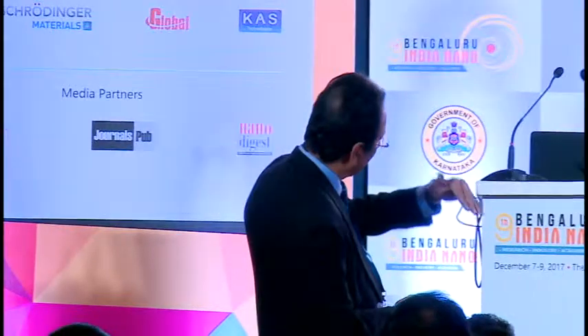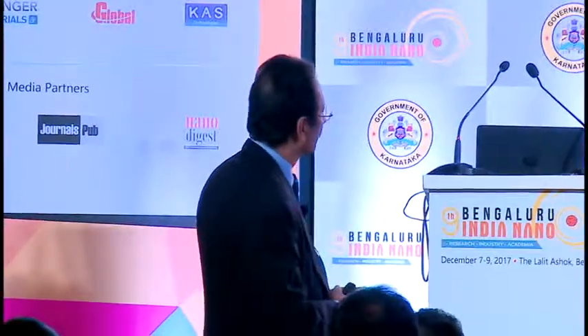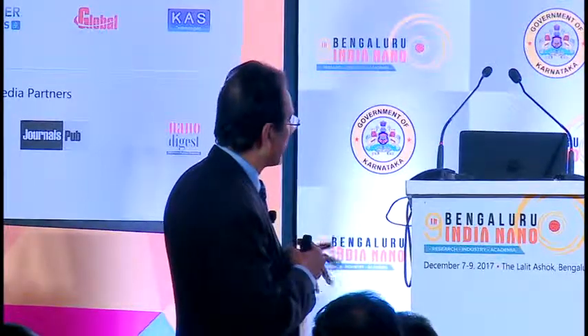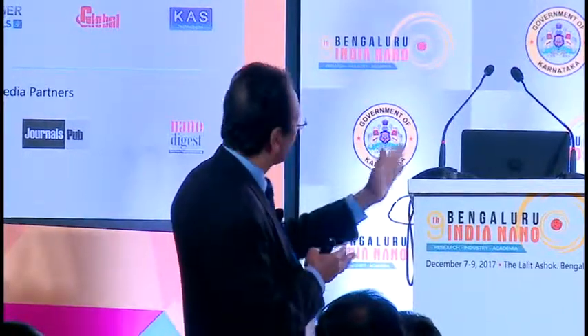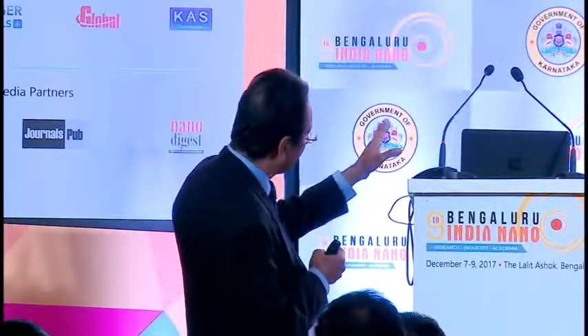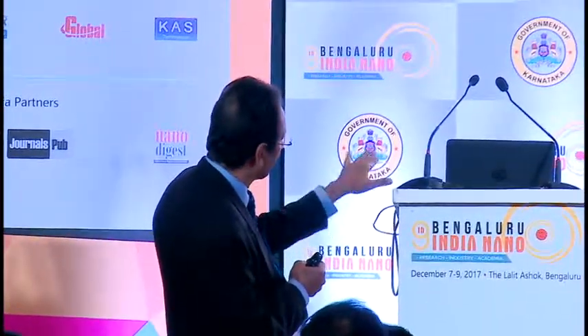Then what we found was that when we looked at the angular dependence of this deposition, there were two components to it. There's a strongly forward-directed component, and then there's a shallow component, shown with a dashed line, which is the cosine theta component. That is the conventional evaporation, whereas the forward-directed component is what is called non-equilibrium, forward-directed evaporation. If you look below it, the compositions are shown, and you can see that the copper to yttrium ratio is 3 only in the forward-directed angle, barium to yttrium is 2, and copper to barium is basically 1.5, which is exactly what you would expect.